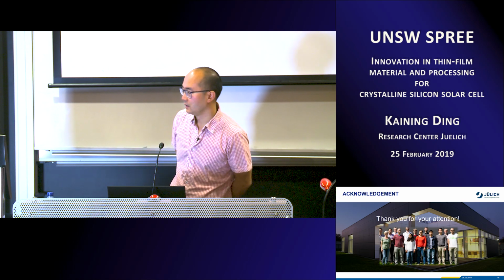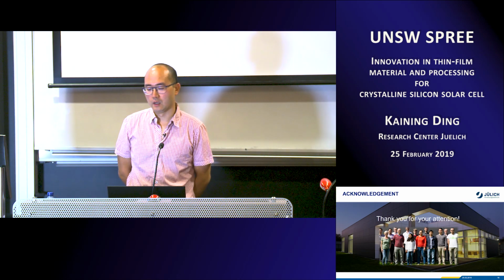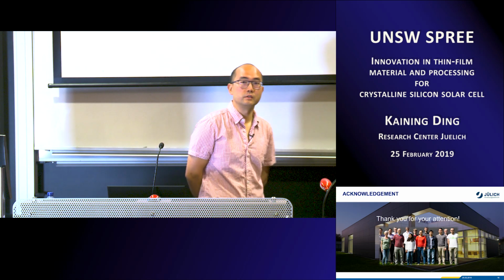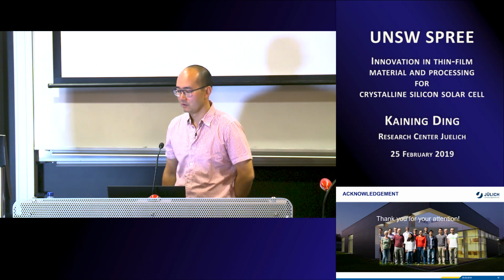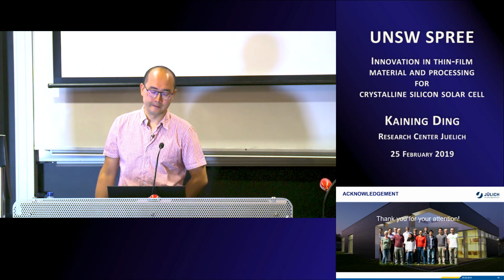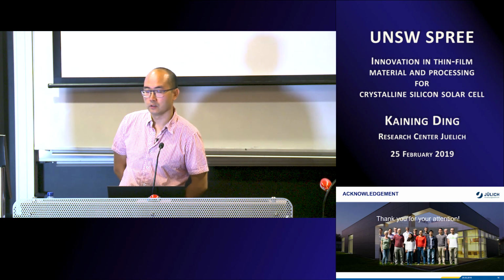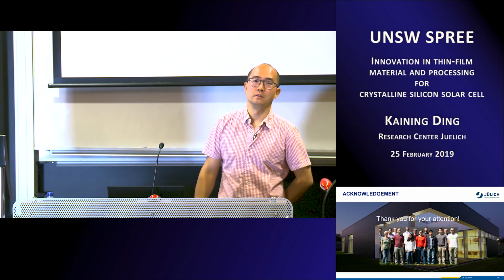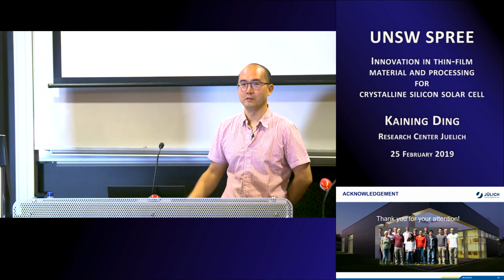So as I mentioned, on that topic we're not working on process technology. I know the yield is quite low, so there are a lot of breakages during the processing, especially between 40 and 80 microns, so you have the valley of death for the wafers. But with manual processing, so we are not talking about machines selecting the wafers, people can learn how to deal with them. So the breakage rate at the moment is quite low, but in the beginning it was maybe every second wafer.